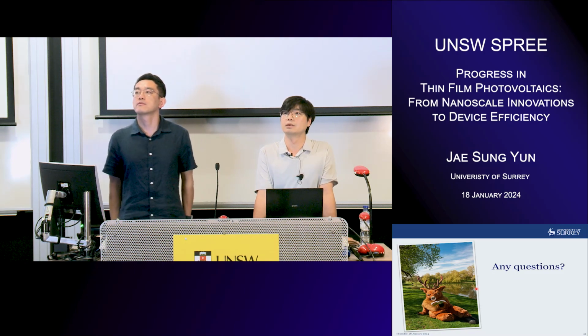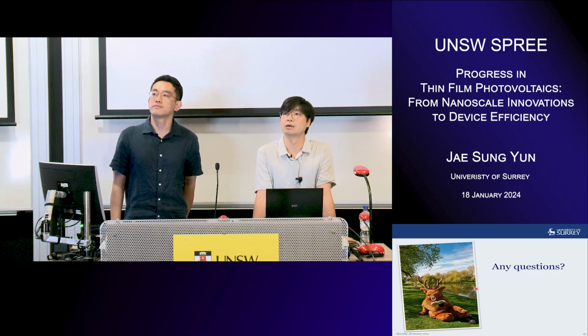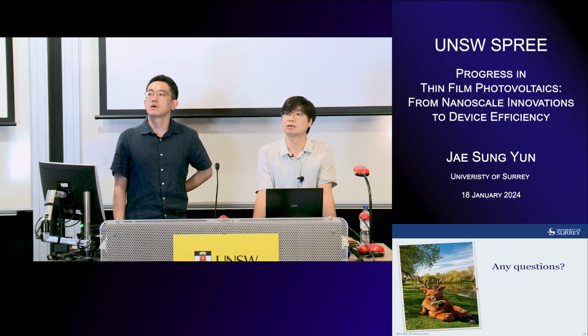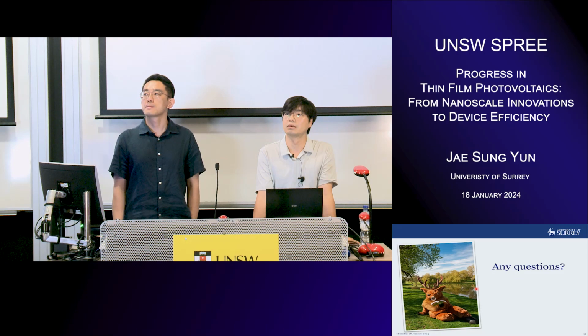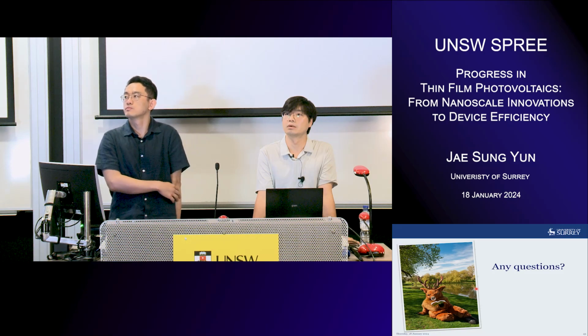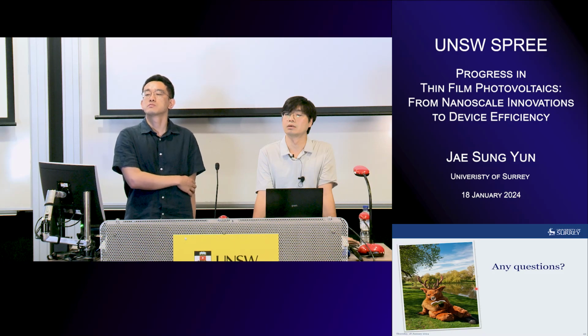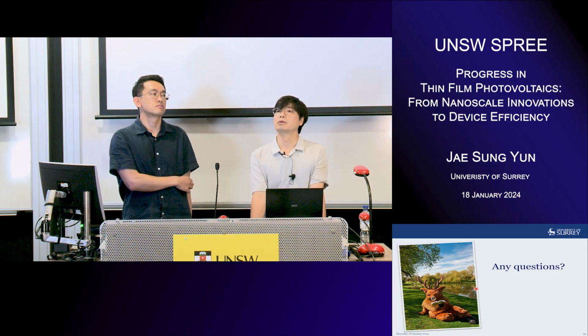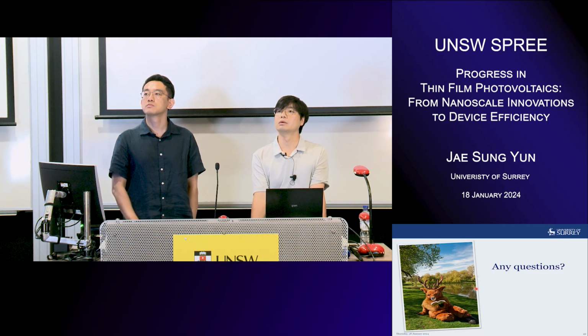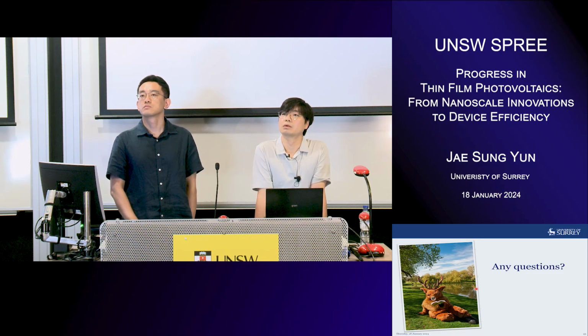Hi, this is Xiaojing from Surrey. Very nice presentation, particularly in terms of phase segregation and also the stability issue. I think that's critically important for the perovskite field. One question: you mentioned that when increasing the concentration of bromide in the perovskite, you see more severe phase segregation. And you pointed out that currently 5% seems okay. But I believe all the characterization was done at room temperature or around 30 degrees. So I was wondering, for the 5% bromide, if you apply 85 degrees, do you think this needs to be further reduced, or do we need to have bromide-free perovskite?